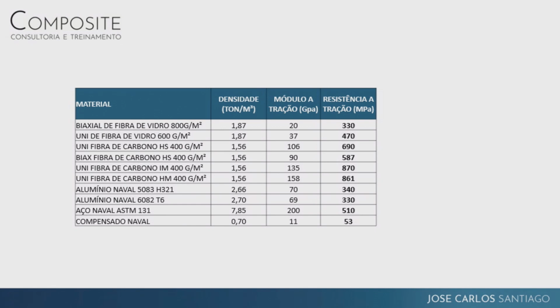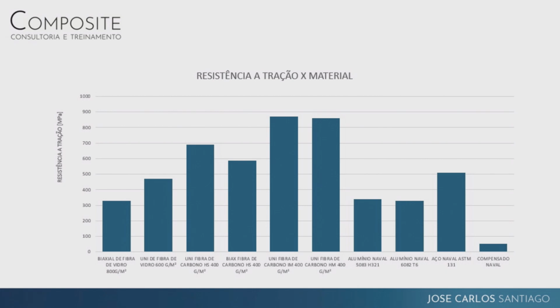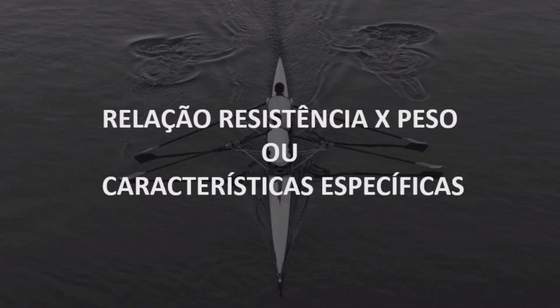Then you have traction resistance. We have carbon fiber, the standards that are usual that we find have this resistance over steel. It's not so relevant for us to consider only the strength, because if we think about only strength, aluminum and steel have good strength compared to glass fiber, but that's not what we see usually in the smaller boats, 50, 60, 80 feet and under. We see that a lot of glass fiber and carbon fiber is used, and that happens because of the specific resistance. So it's the relationship that we have between the strength and the density of this type of material.